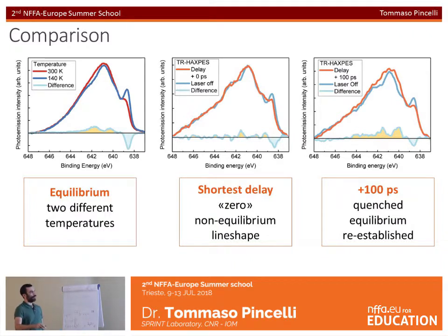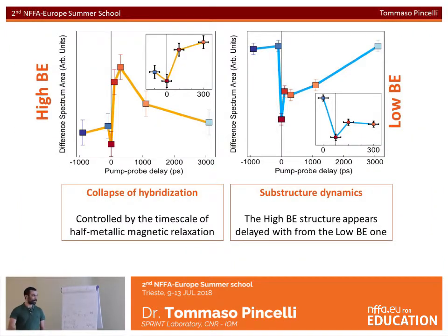And if we go to longer delays, we see that instead the variation of the line shape is much more similar to the one of equilibrium variations of the temperature. So we can look at the collapse of hybridization, and we can say that it takes extremely long times. So that is controlled by the time scale of the magnetic relaxation. So we can answer that question: if magnetization kept the system active and metallic, that's yes. And also we have hints of the fact that we have substructure dynamics.